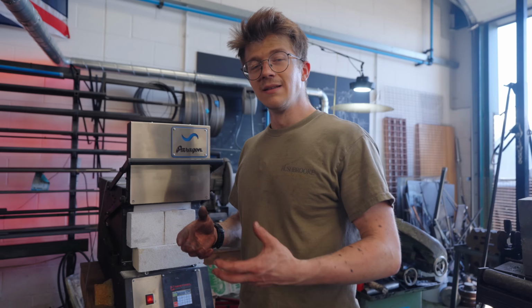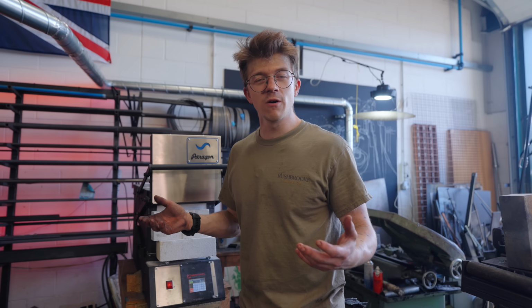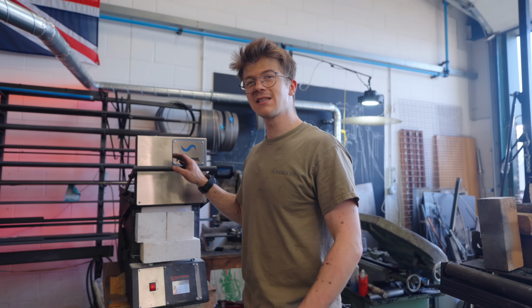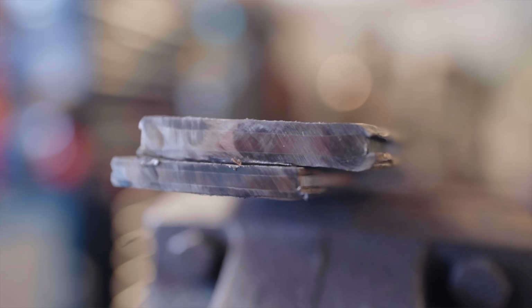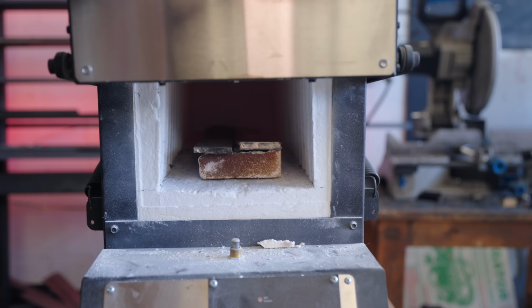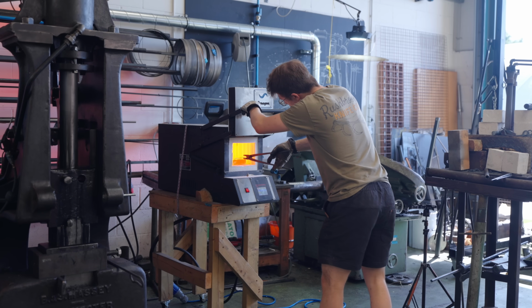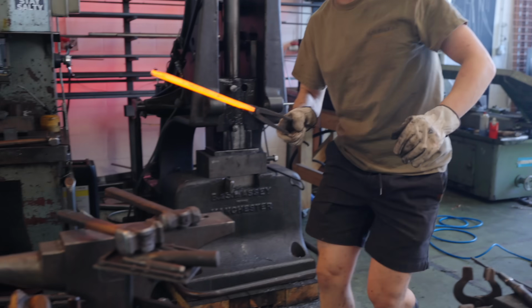Now, the thing is, now that these pieces are all bonded together, no more oxygen can get inside there, which means we can crank the temperature, go a little bit hotter, forge them out without the jacket or the argon shielding. So we can now go up to 1,050 degrees Celsius. Okay, start on the thick one.